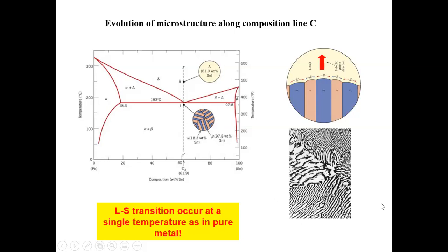Okay, and it's not an electron microscopy image, right? I don't know. I think optical image is good enough to show this. You just polish the sample and you do some etching, and then different phases are going to have different etching depths, and then this will show the signal using optics. I don't think it's SEM because the features are too large. Yeah. Okay. Thank you. That's eutectic, right?